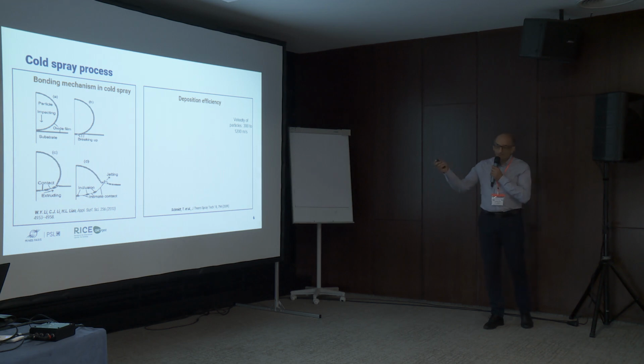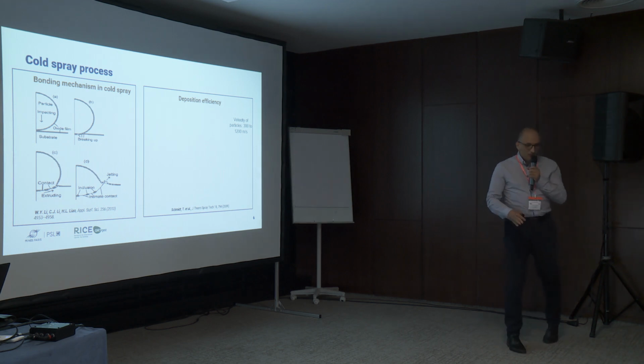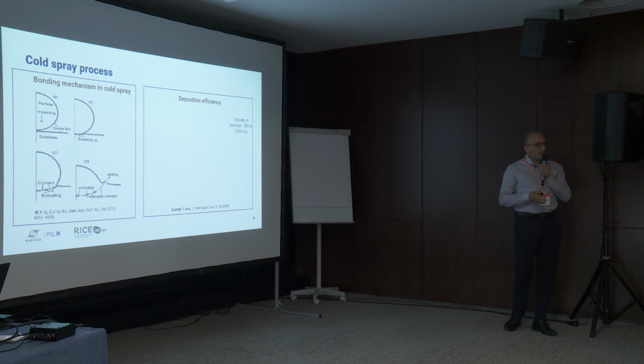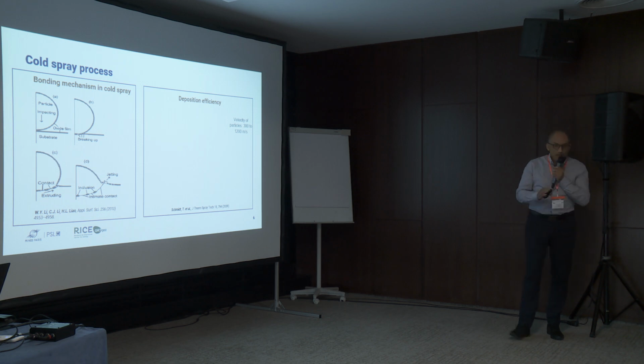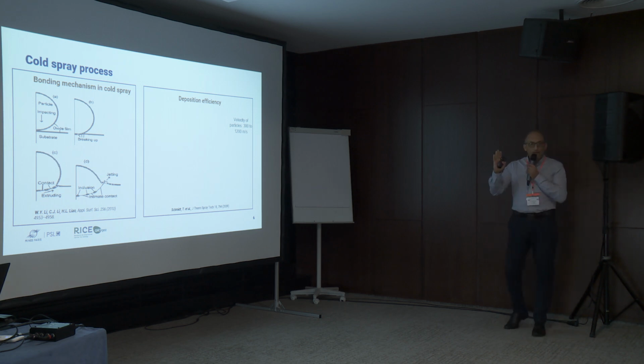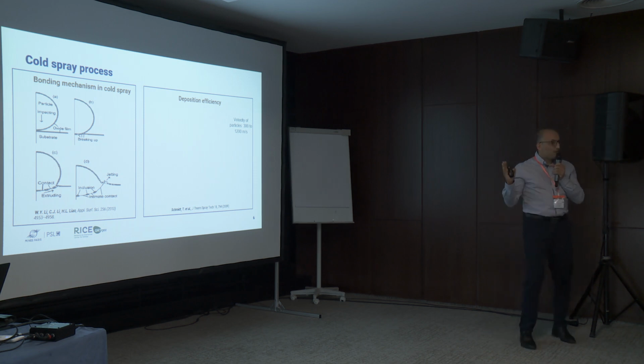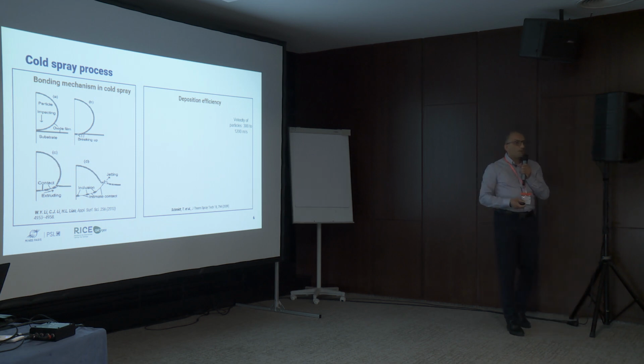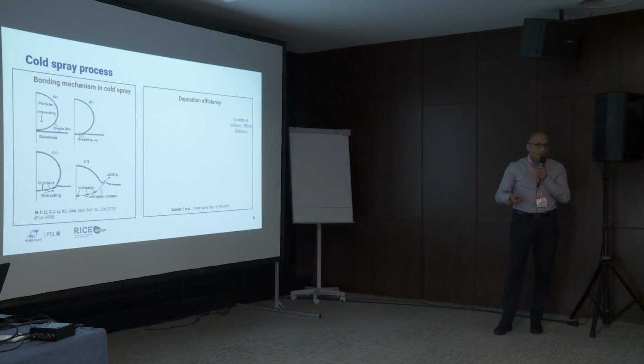Okay, so here you have a figure showing the deposition efficiency, because we have a critical velocity below which you have no deposition, and you have a window between this minimum velocity and a maximum velocity. Over that, you have an erosive effect of the particles, and again no deposition. So sorry for that.